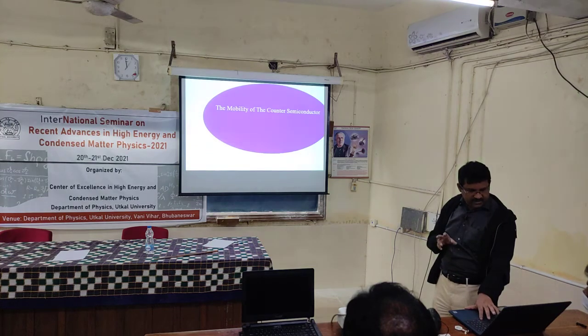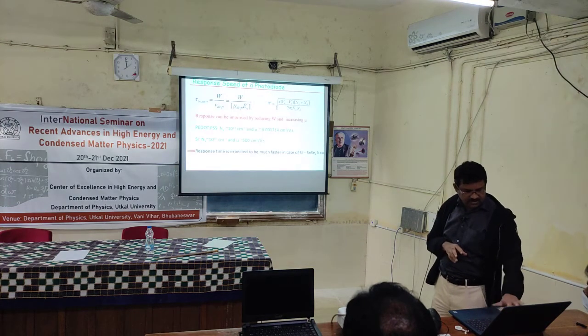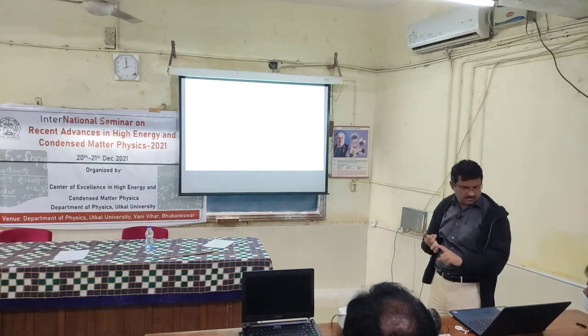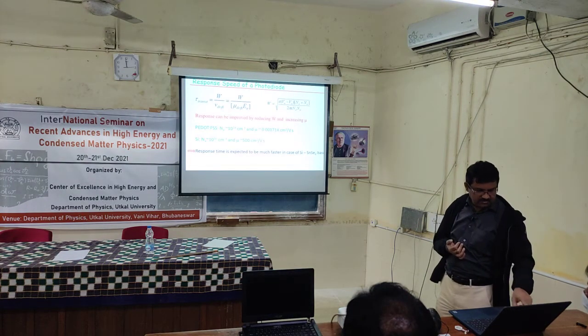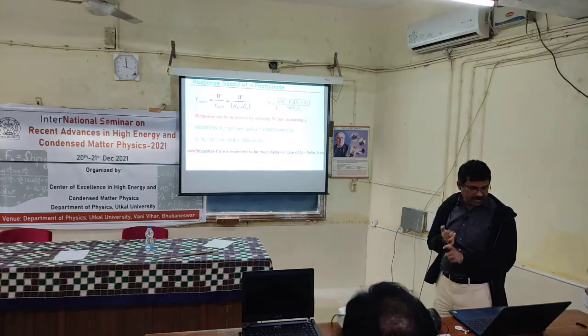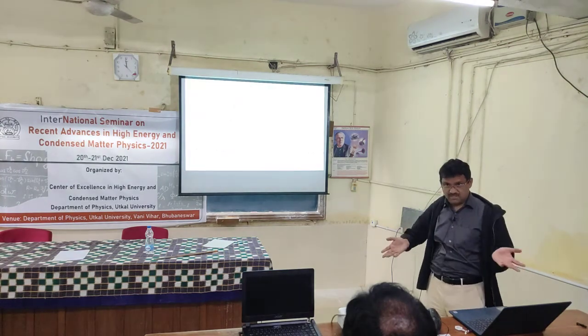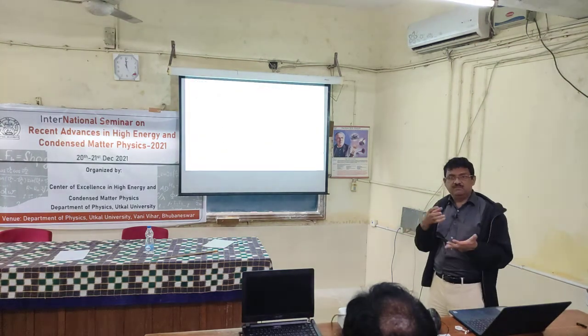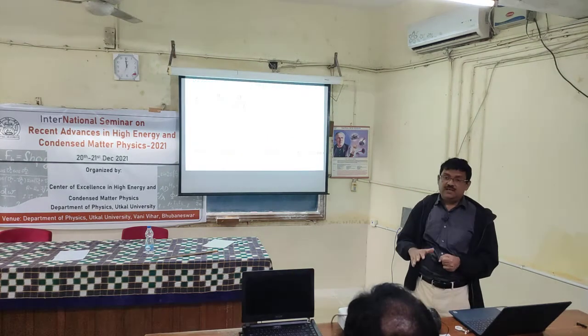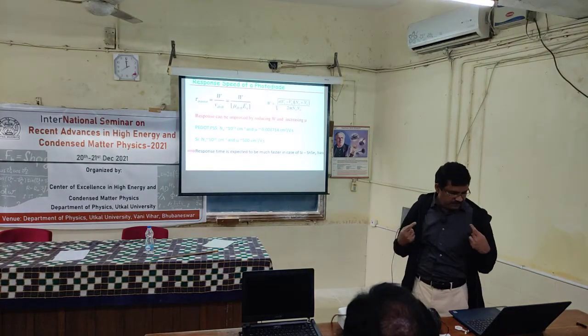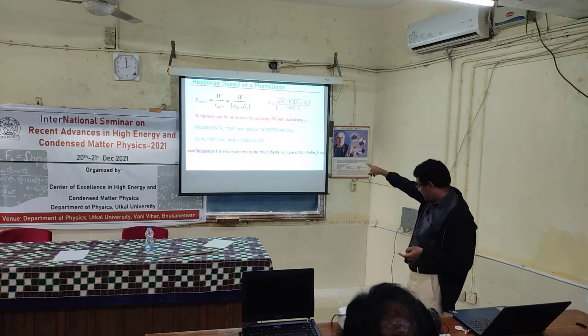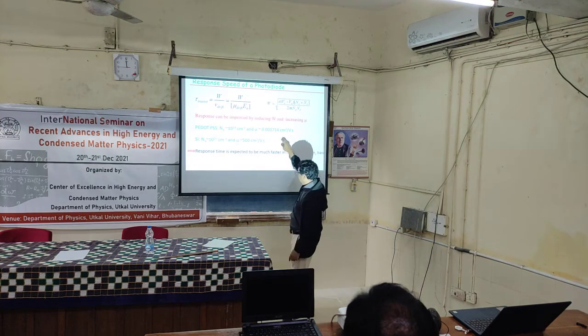So what we did, we looked at these equations again, the mobility, and say for example the concentration. Then we realized that silicon can be a material, p-type silicon, which is also available commercially. We don't have to deal with doping silicon, it is available. In fact, we supported it, and then we deposited SnSe2 on p-type silicon. Because the mobility, as you see, this is the mobility of PEDOT:PSS, and this is the mobility of silicon.